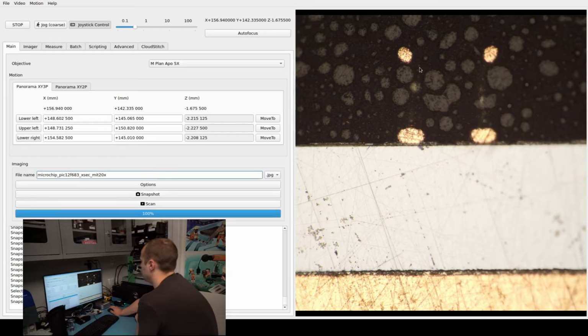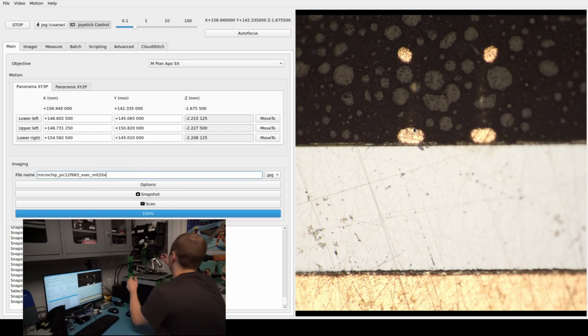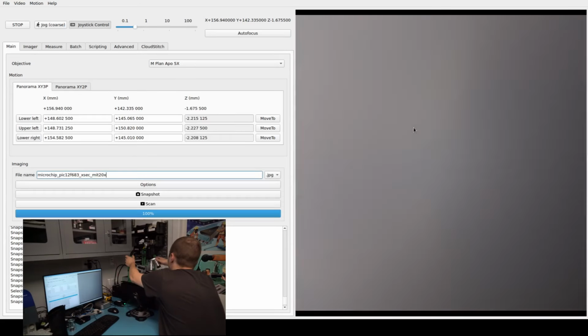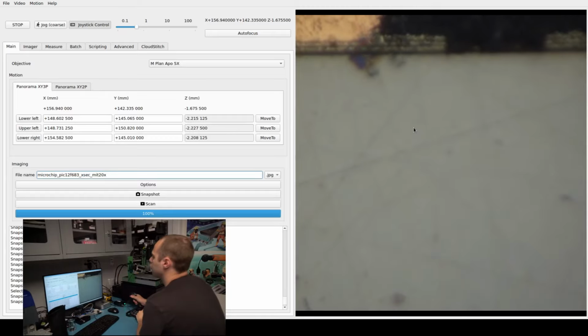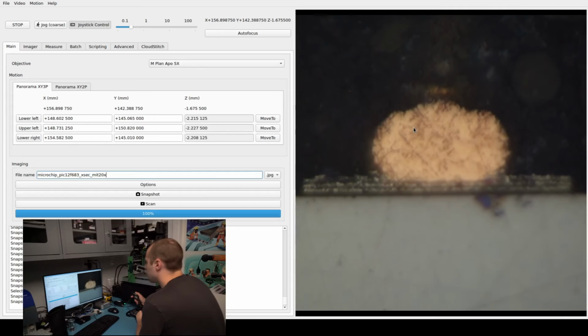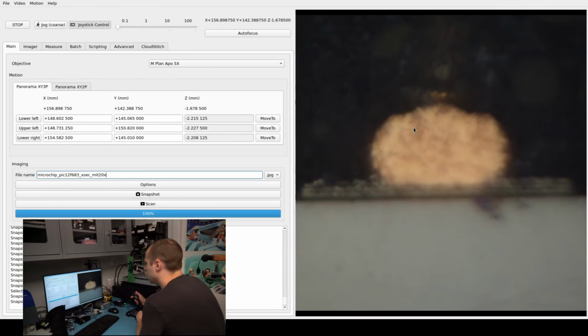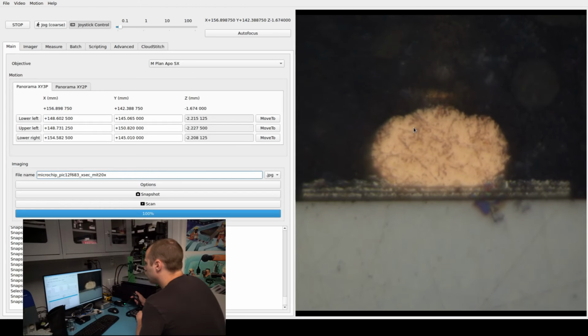The ball bonds are now in section. We have not quite got to the center line of the wire, but we're in the wire bonds, and we just want to go back probably another 5-10 microns to get into the wire itself, and we'll be at a perfect stopping point. And zooming in a little closer, we can see we've got 3 aluminum metal layers and then the gold ball bond on top of that.